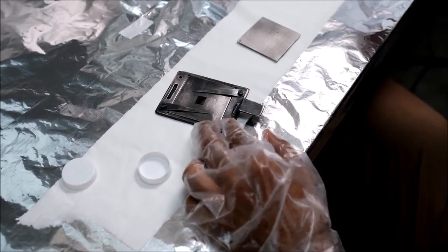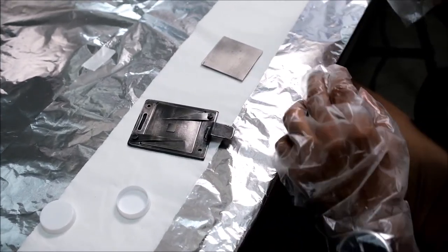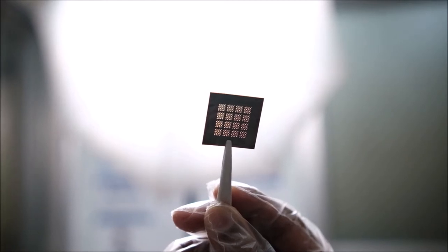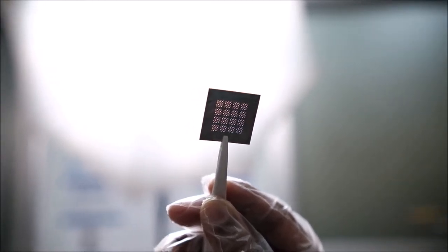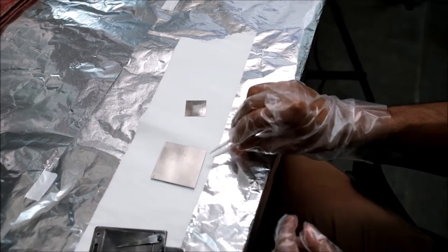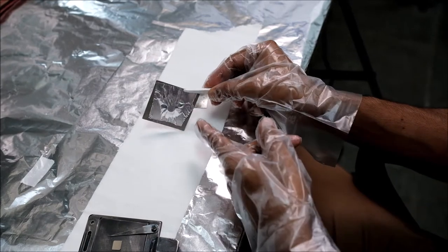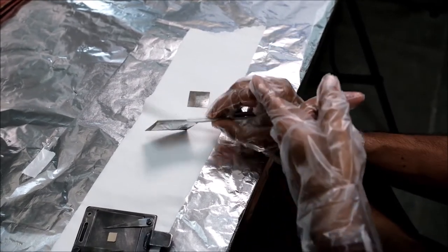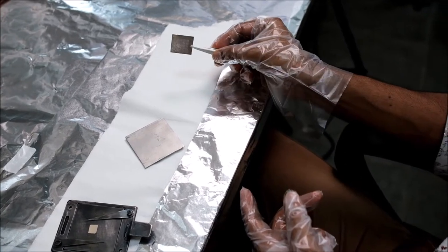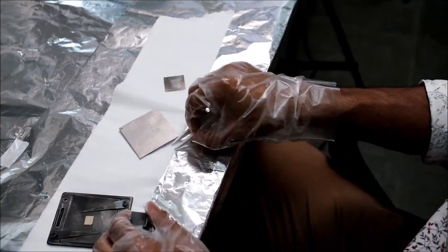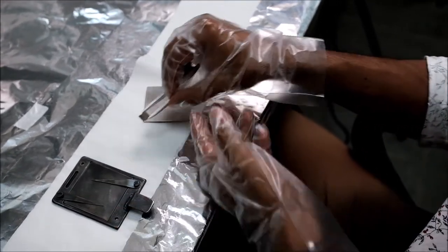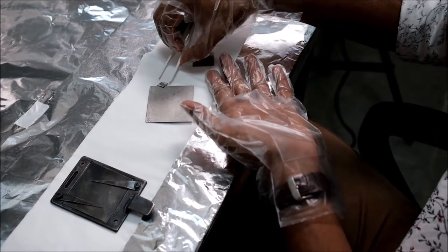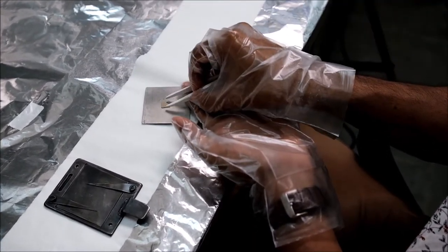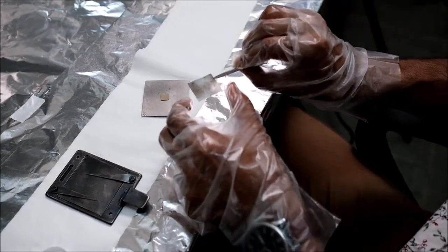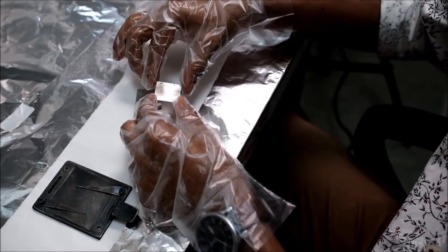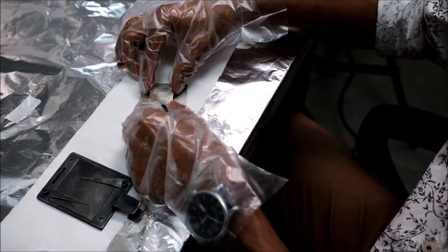So this is done by this metal shadow mask. Here you see the metal shadow mask, a pattern is already made there, and this is made of nickel material. This is a plate, and at the back of it there is a magnet placed, so the magnet can attract this nickel metal shadow mask, and thus it can attach to our substrate. So we will hold the substrate at the middle of the plate, and then carefully we will put the mask onto the substrate. We have to be careful because it attracts the magnet.